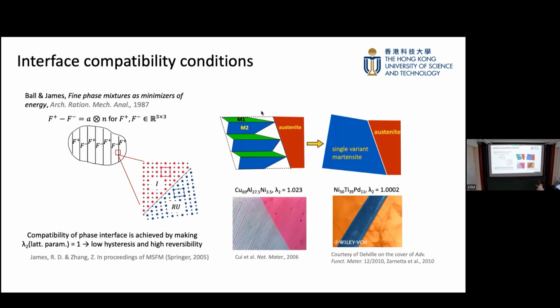And here, a microstructure implication is that we have a reference austenite. Usually, the lattice parameters cannot naturally satisfy that. But after some chemical tuning makes the material satisfy that equation, then this single variant can perfectly fit with the austenite lattice through this very sharp and lattice-distortion-free interface.